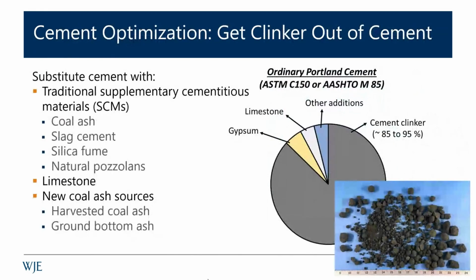So the way that we can optimize cement, getting that clinker out of the cement, is through those traditional supplementary cementitious materials that I've been talking about. Coal ash, we no longer just refer to fly ash, because now ASTM C618 allows for bottom ash and fly ash; you can grind bottom ash combined with fly ash or use bottom ash. And this allows us to actually harvest coal ash. Slag cement is one you're familiar with. Silica fume, I think you're familiar with based on your specs. And then natural pozzolan. So those are our basic traditional SCMs available to us.